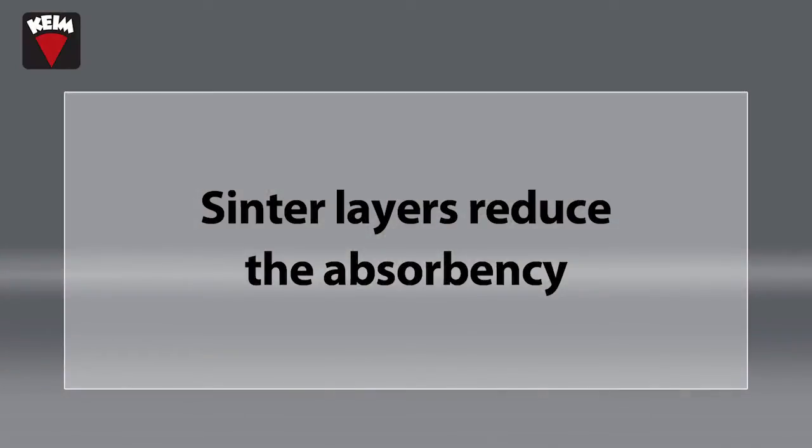This layer turns into a thin, compact skin which restricts the paint binder from penetrating into the substrate to form a strong chemical bond. This is why the sinter layers must be removed prior to coating.